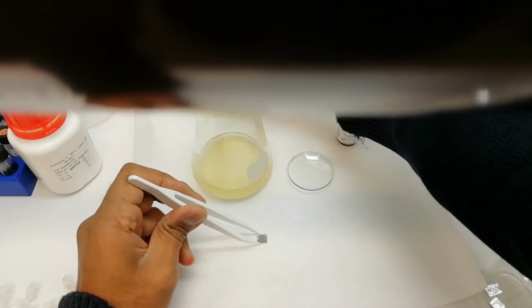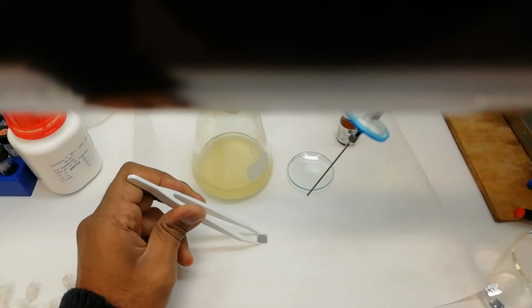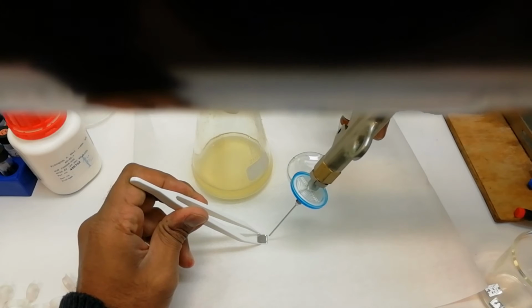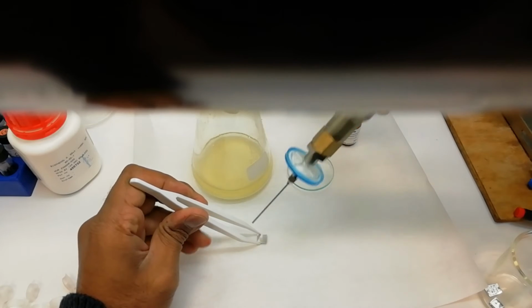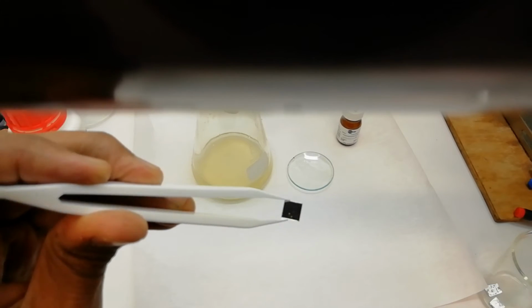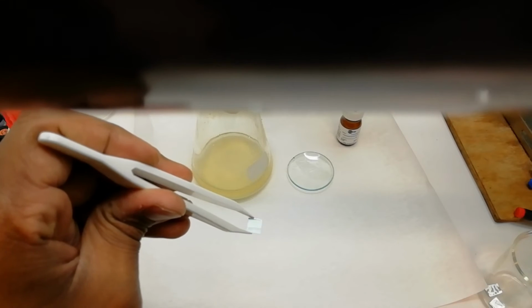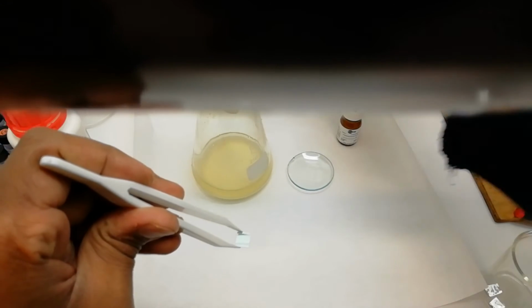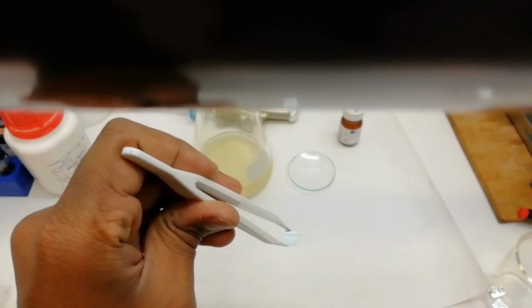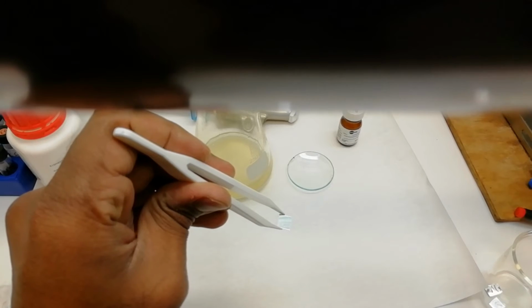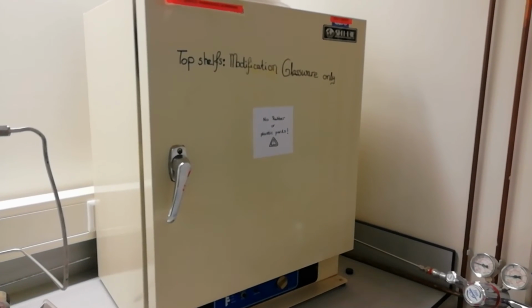Finally, surfaces are heated at 100 degrees Celsius under vacuum for 1 hour. Because it requires thermal annealing or curing after deposition of a thin phosphonic acid film, it was proposed that the phosphonic acid molecules in the unheated, as-deposited film are only weakly bound on the surface.